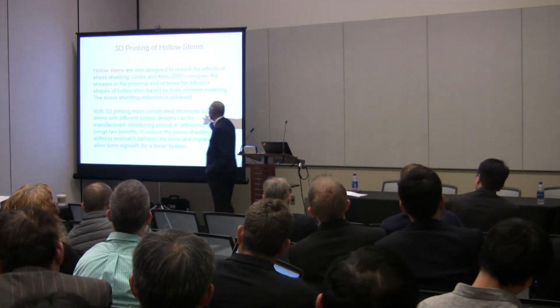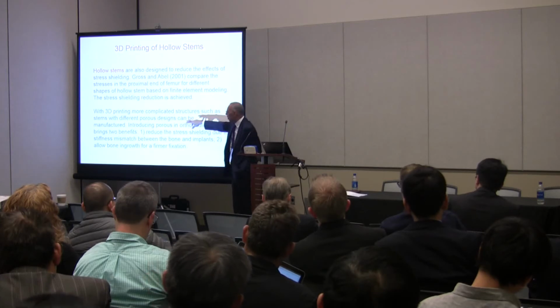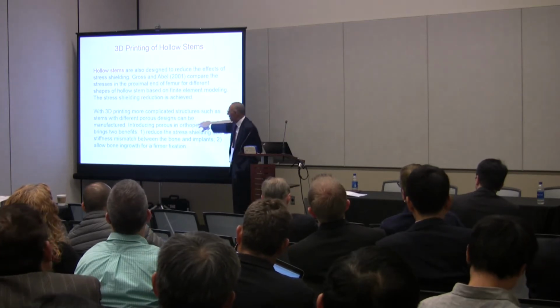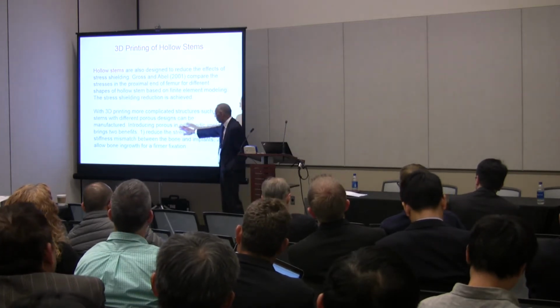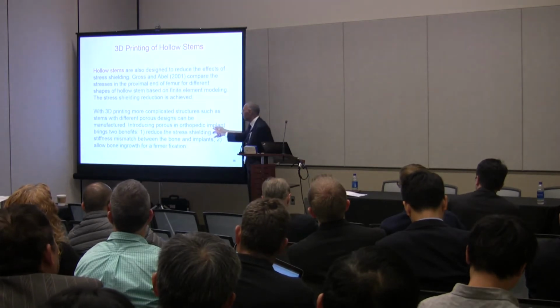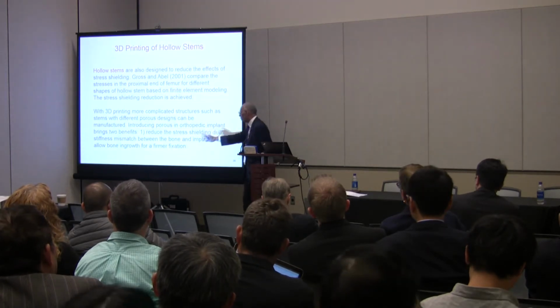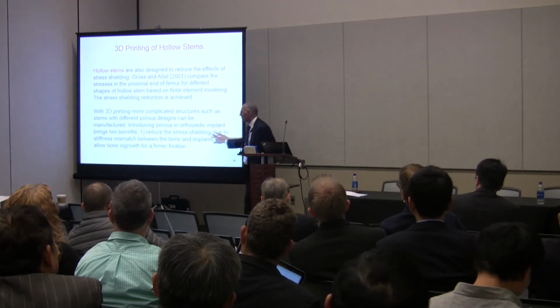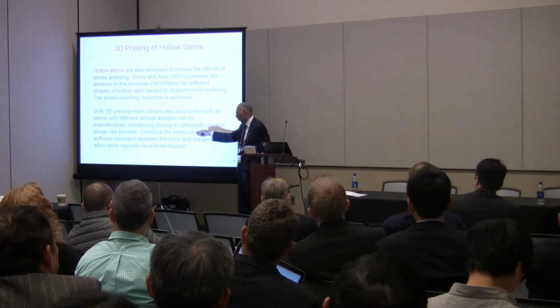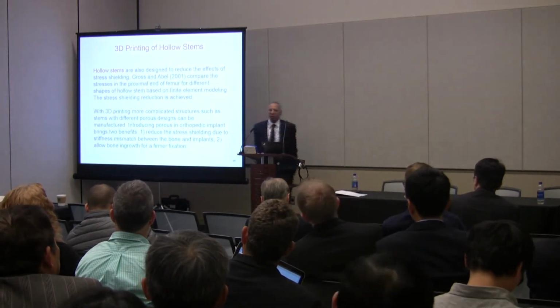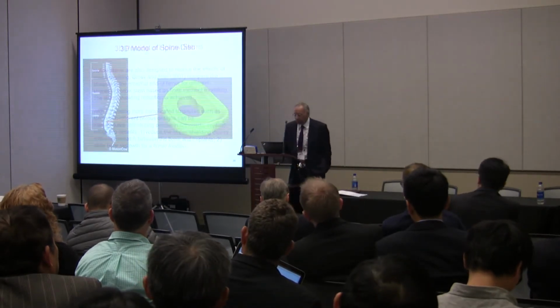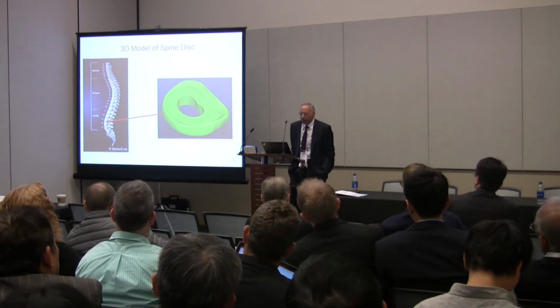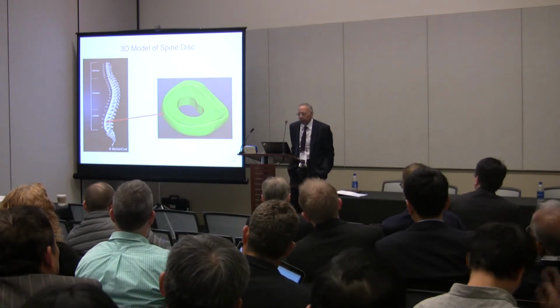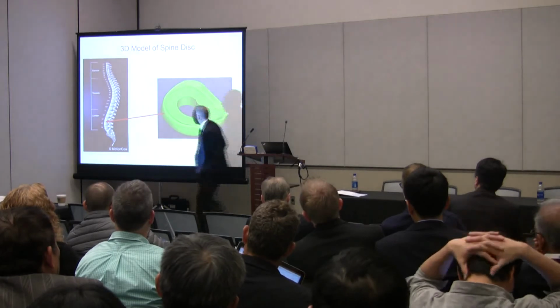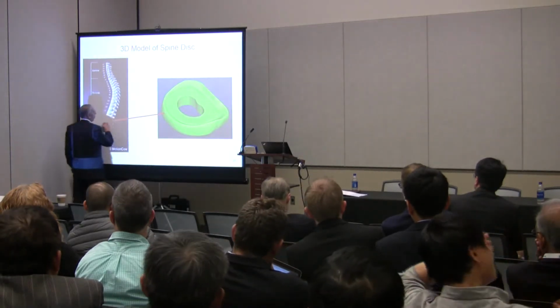3D printing, complicated structures such as stems with different porous designs can be manufactured. In these, it can introduce porous into orthopedic implant that brings two benefits. It reduces the stress shielding due to the stiffness mismatch between the metal and the bone, and indeed allows bone ingrowth for firmer fixation. So here is a disc. And this is a project we tried to do. You get the spot that, I don't know what disc number this is. This is the lumbar, disc 4 from bottom.